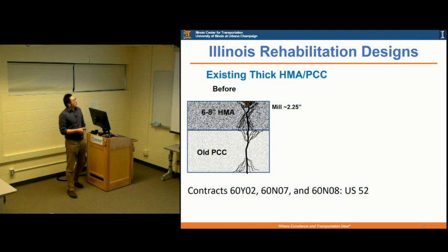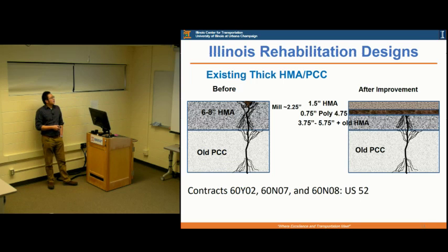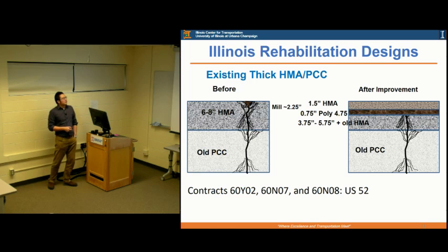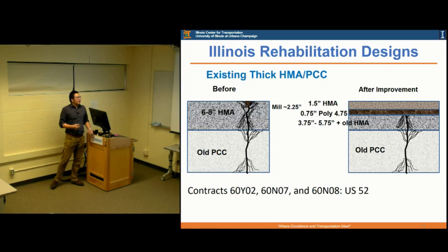This is another example. We are trying to remove that very bad condition, to remove those distresses through the milling. And then you put a polymer modified binder, basically a less than 1 inch level binder course, and then put an HMA overlay. So this is our rehabilitation design method right now.